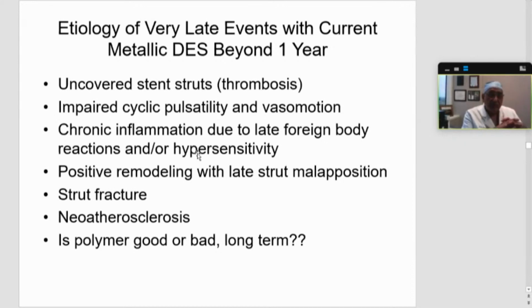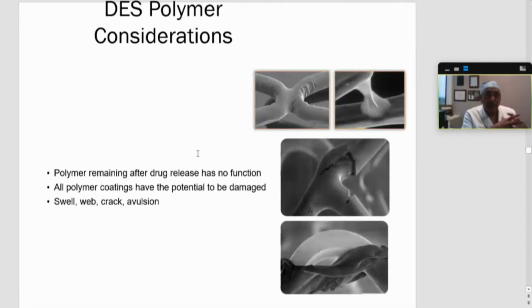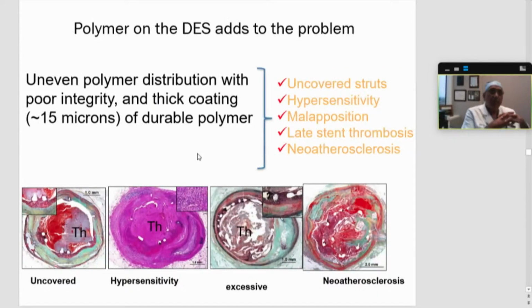And then obviously there is the debate about polymer, whether it's good or bad, and whether we have to always give it. Can it be absorbable, and so on and so forth? Because polymer is there after the drug is eluted, whether you give it for 60 days, 90 days, or 120 days. The polymer is there forever, and those can be damaged. They can swell, they can web, they can crack. There have also been electron microscopy studies of the evolution of polymer. Polymer on the DES adds to the problem potentially.